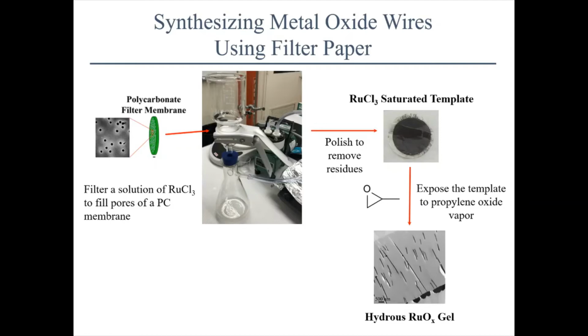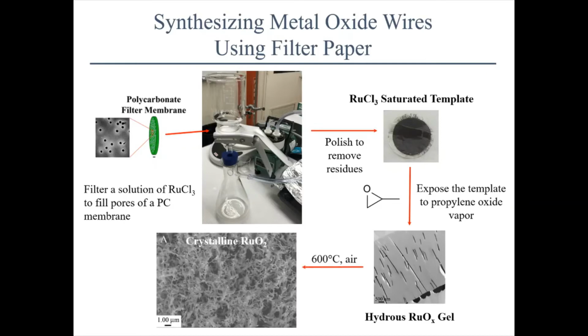So we had to rethink things, and we developed a new process where we took the ruthenium chloride, but as a sol, we loaded the pores with it, and then we developed a new reactor where we could take that template and expose it to propylene oxide vapors. In essence, we had our sol inside the pore, and then we infused the gelling agent as a vapor into the pore, and caused the sol-gel chemistry to take place in situ inside the template pore. So we formed our hydrous ruthenium oxide gel inside that template pore, and then when we annealed, we got a very morphologically pure sample of crystalline ruthenium oxide. That was something a little different that we developed for this particular project: a new way of gelling the ruthenium oxide directly in the pore.